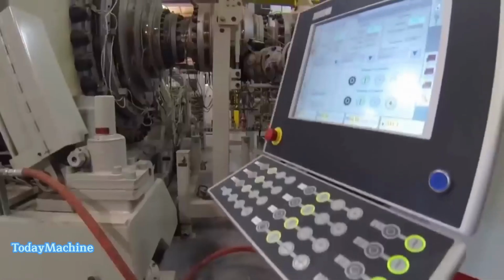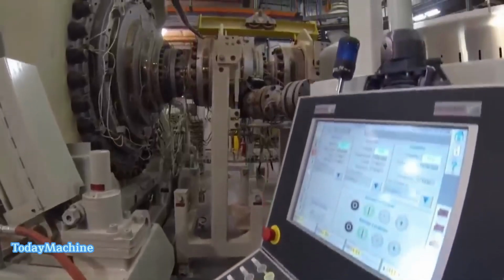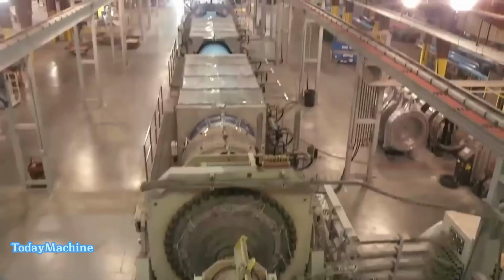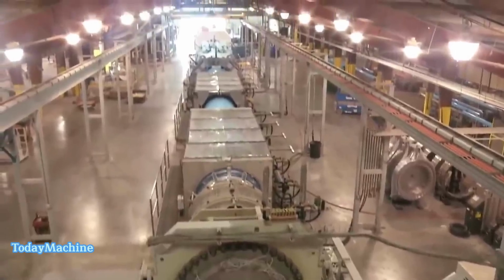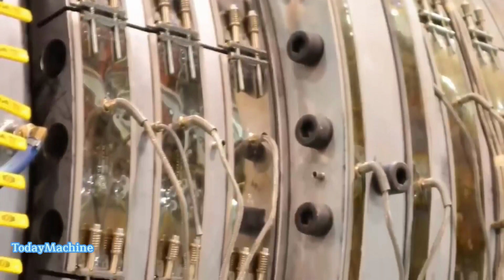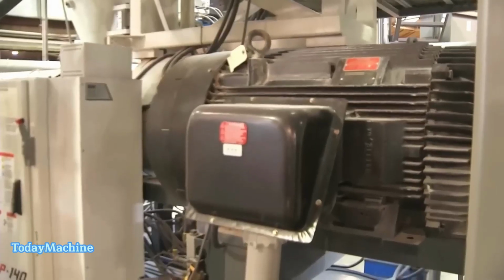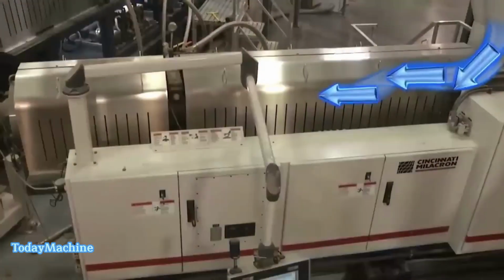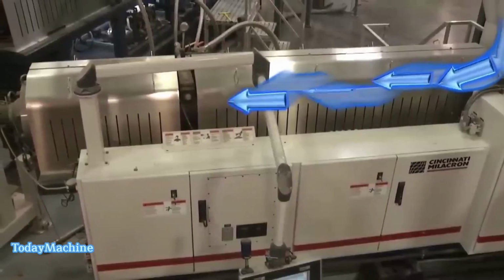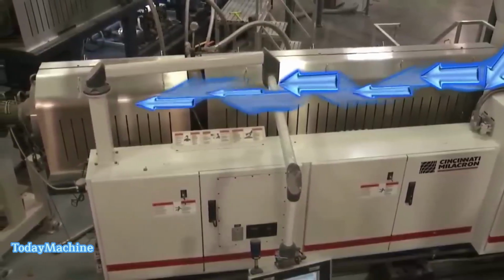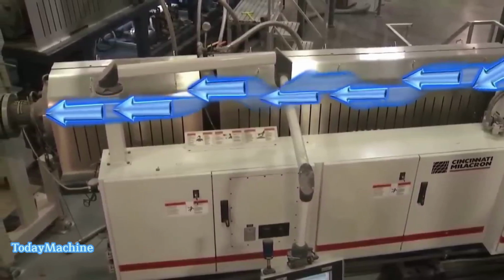The compound enters the extruder and is compressed and heated by the screws, transforming it into a hot and pliable material. The extruded PVC material passes through an extrusion die, which consists of several components held at precise temperatures above 300 degrees Fahrenheit. The die culminates in a sizing sleeve that determines the outside diameter of the pipe.